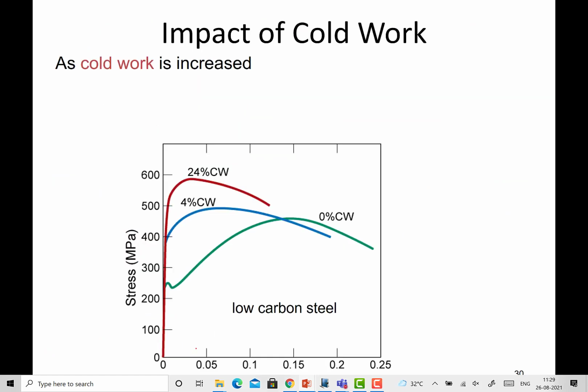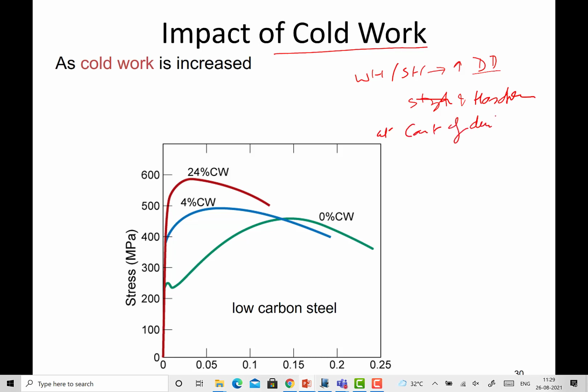I hope this is a very simple thing about which you will be knowing. Work hardening or strain hardening will be increasing the dislocation density, and because of that your strength and hardness both will be increasing, but at the cost of your ductility and mostly the toughness as well. This is what you can see when a simple low carbon steel is subjected to different values of deformation, that's cold working, to different percentages, say 0%, 4% and 24%, the way by which the properties change.